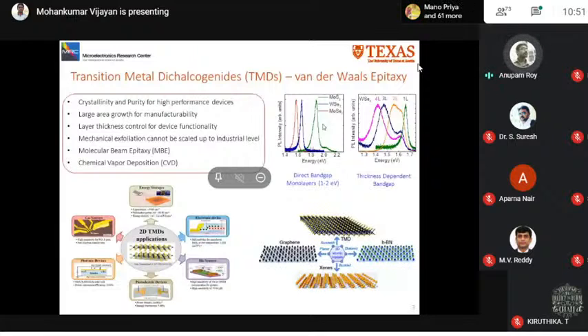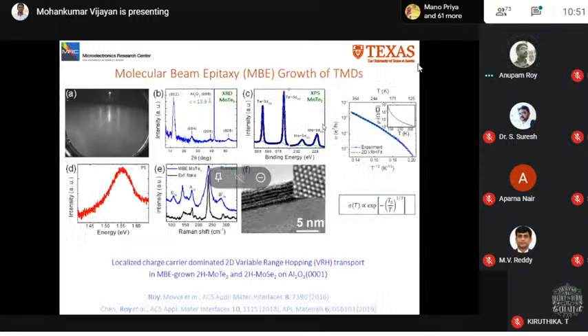In the next slide, we previously reported for the first time the hexagonal MoSe2 and MoTe2 growth via molecular beam epitaxy, and you can see sharp streaks in the reflection high energy electron diffraction pattern.